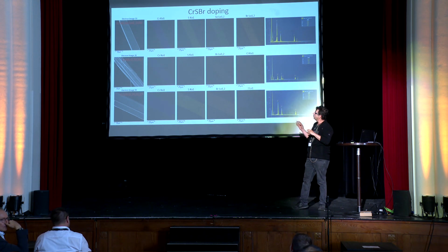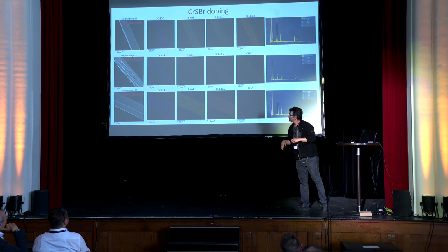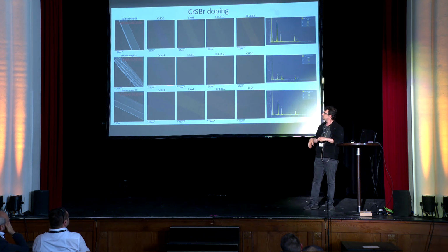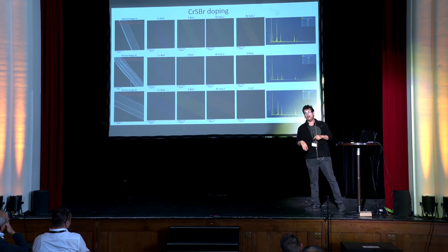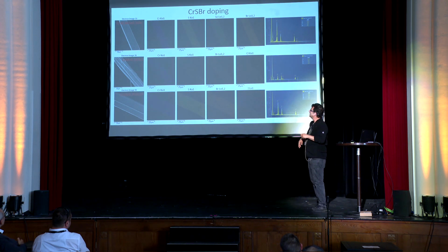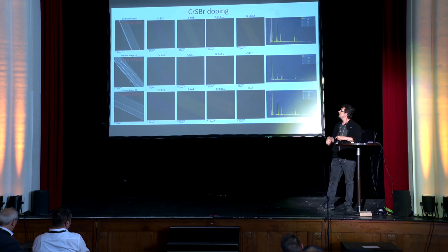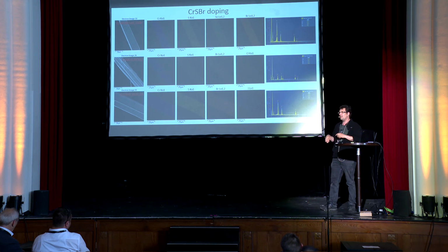But if you want to go for the heavier halogen and heavier chalcogen, like with iodine, we start with 10% in the starting system, and only 5% was incorporated. The same goes for sulfur substitution with selenium and tellurium. Tellurium will probably be finished next week when I arrive back in the lab, but for the selenium, substitution of sulfur at 10 and 20% was possible to achieve. And if someone gets a sample with 10% of chlorine, it was actually an error. It's 10% of selenium in that sample.